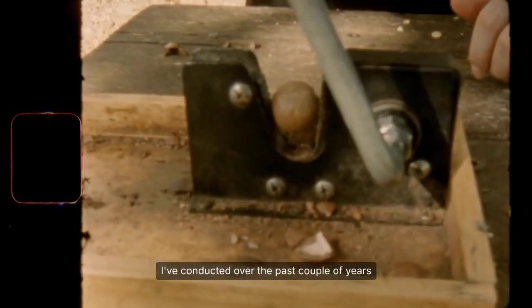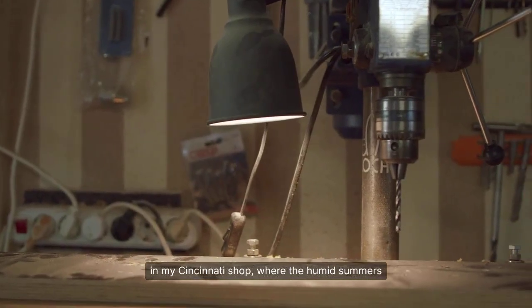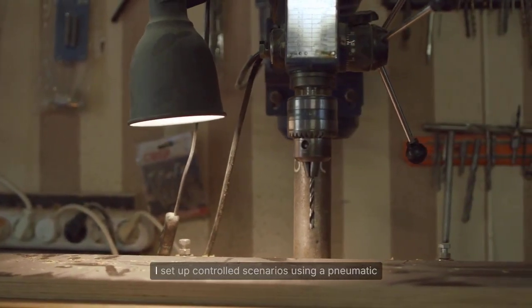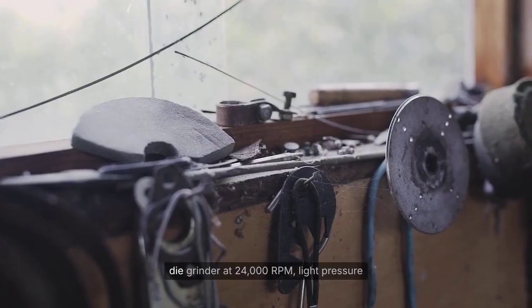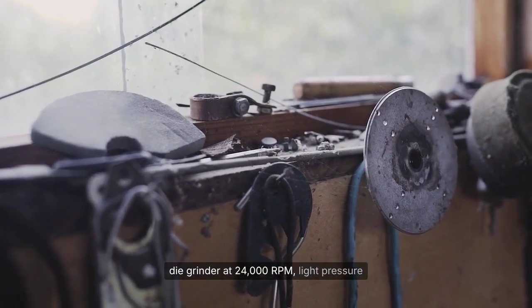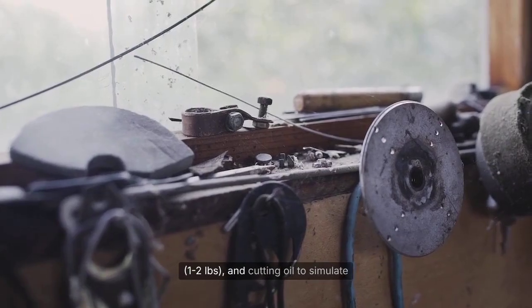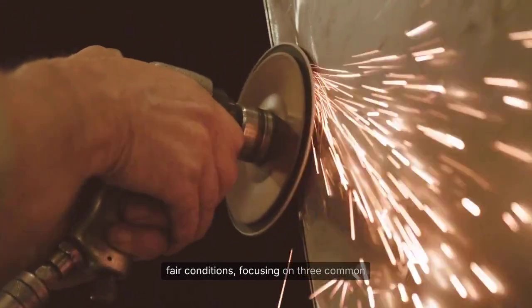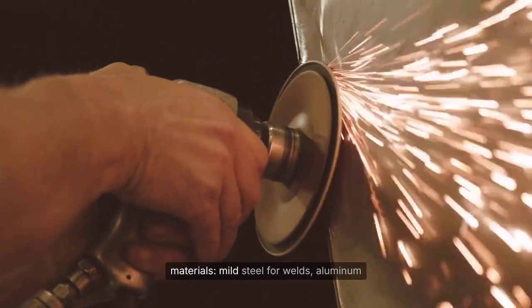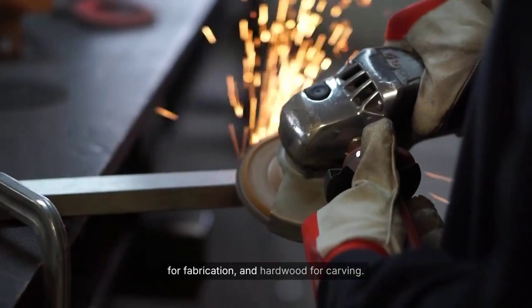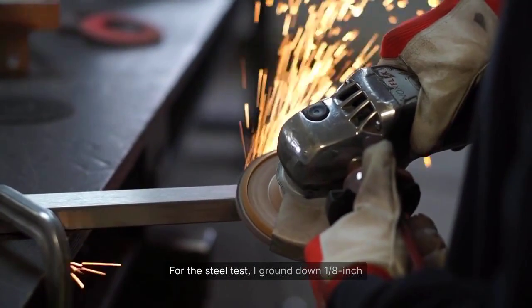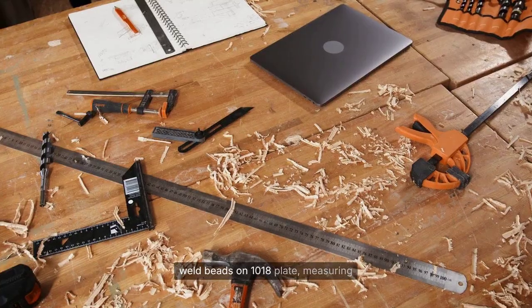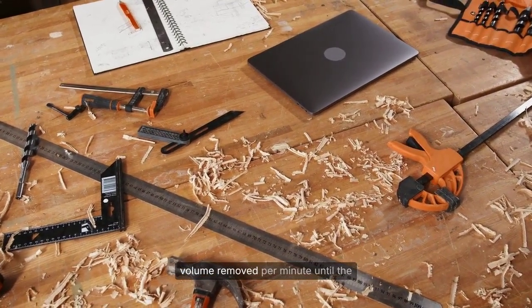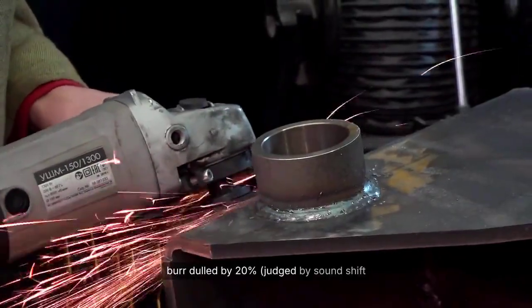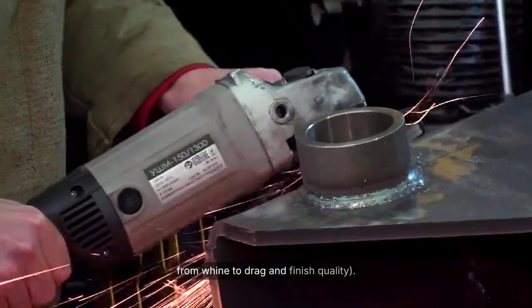Now, for the real-world longevity tests I've conducted over the past couple of years in my Cincinnati shop, where the humid summers and dry winters test tools' resilience. I set up controlled scenarios using a pneumatic die grinder at 24,000 RPM, light pressure, 1 to 2 pounds, and cutting oil to simulate fair conditions, focusing on 3 common materials: mild steel for welds, aluminum for fabrication, and hardwood for carving. For the steel test, I ground down 1/8-inch weld beads on 1018 plate, measuring volume removed per minute until the burr dulled by 20%, judged by sound shift from whine to drag and finish quality.